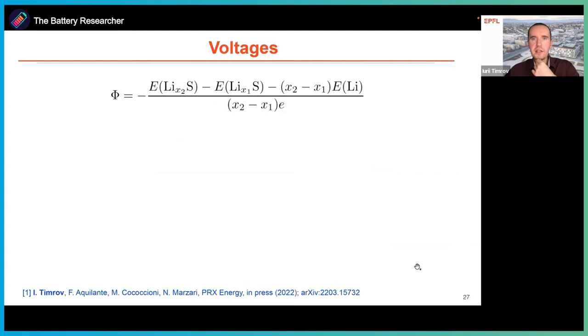Now let us check voltages. We compute voltages using this simple expression. We just need to know the total energies of materials. The first term is the total energy of the material at the concentration of lithium X2. Second term, the same, but at concentration of lithium X1. Then the total energy of bulk lithium. And the difference between concentrations X2 and X1. So here we neglected entropic and pressure-volume effects, as usually done in the literature.